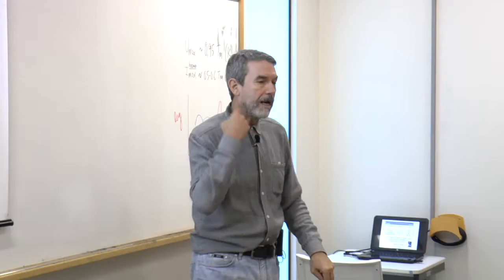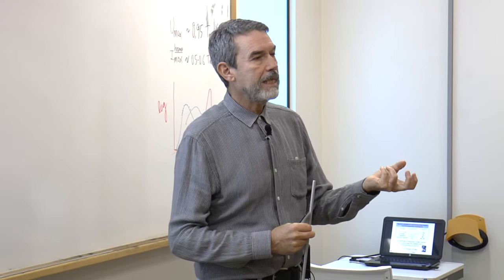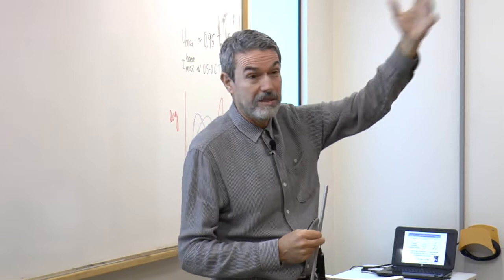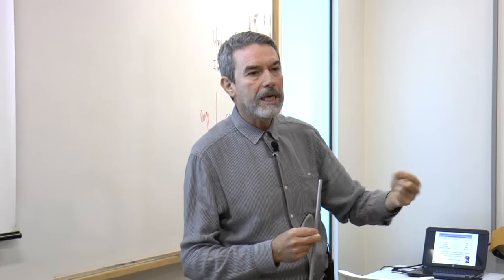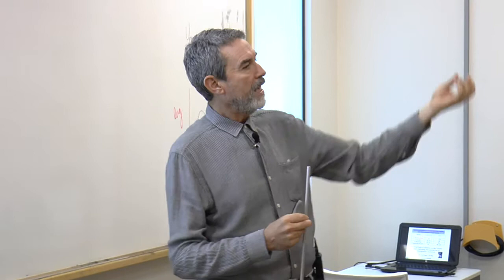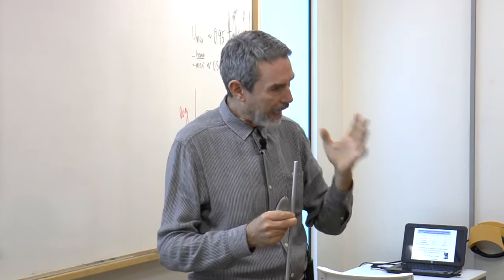In metallic glasses, it's more difficult because metallic glasses do not normally dissolve oxide impurities. So if you have oxide impurities in the air, clay particles, silica dust, and all sorts of things, and you are melting a metallic glass and these oxides drop inside, they will stay there and can act as heterogeneous nucleation sites. In oxide glass making, we are lucky because any of these particles coming from the air are melted and dissolve. They're no longer oxides. They're ionic species dissolved in that sea of oxygen.